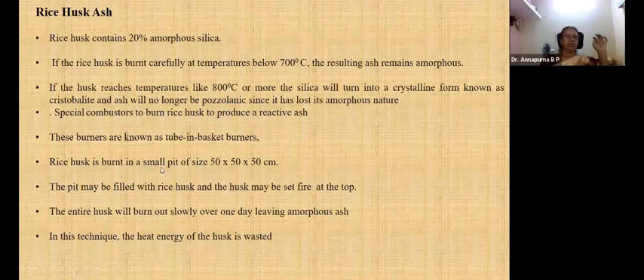Here it is burnt in small pits, like 50 by 50 by 50 centimeters, and we also call it a basket burner. It can also be a larger one. You fill the pit with rice husk and set fire at the top, and leave it for burning. After 1 day, everything will be burned and the ash will be left.